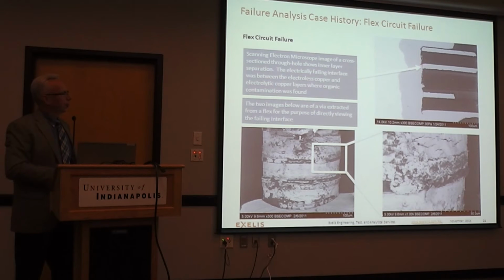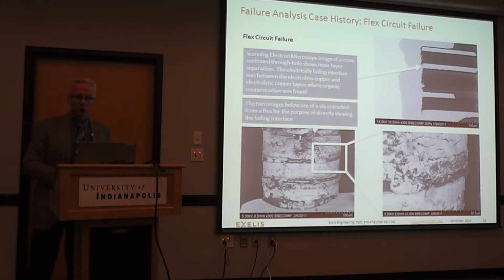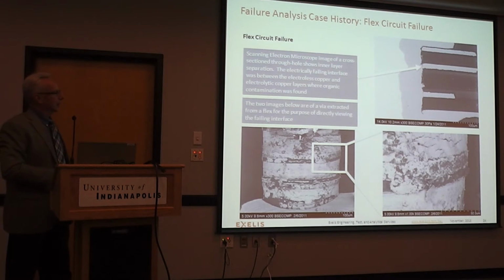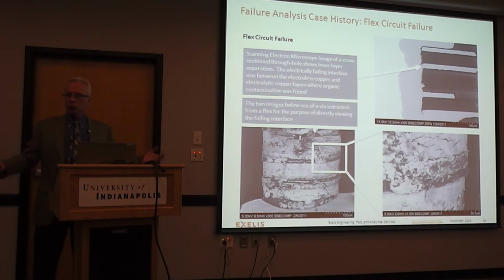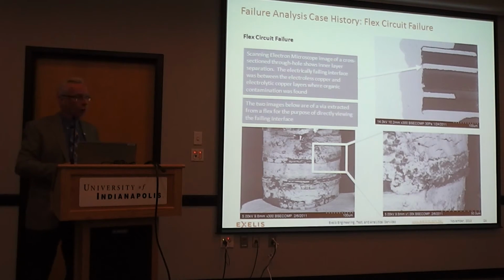And you see this narrow demarcation. There should be no line here. That should be all continuous copper. And you can see this trace is a little bit healthier, but overall, this plated through hole has problems. It's an unhealthy one. In a healthy plated through hole, this should all be continuous. Okay, and so, all right, if you start down the list of why did the circuit fail? Well, this via plated through hole had electrically open T-joints. Why were the T-joints open?